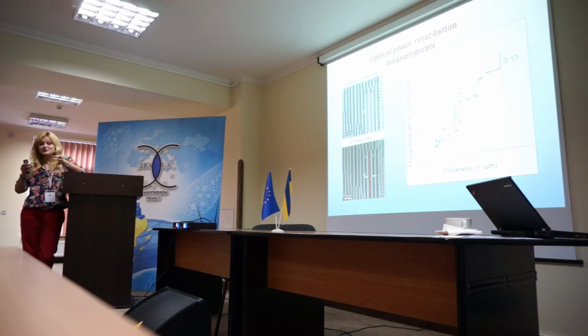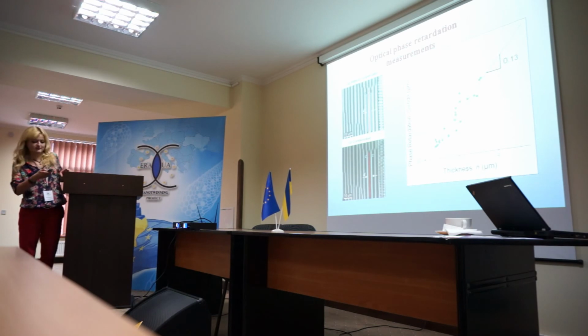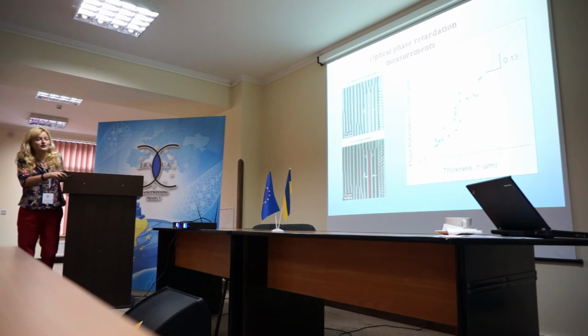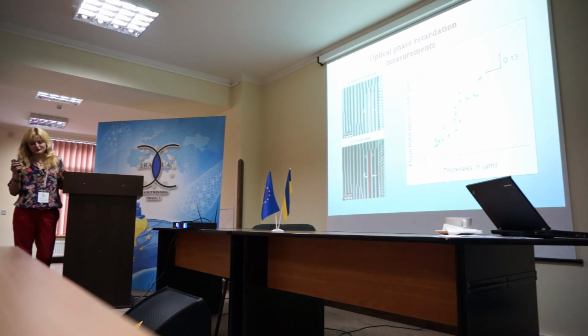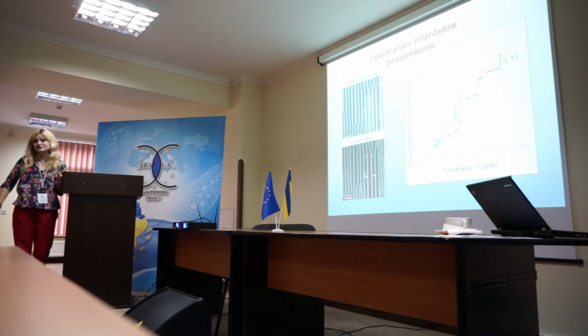We have an optical microscope, we insert a compensator, and when you're looking at the brightest region of the defect, you use a tilt compensator to change it from the brightest to the darkest, and it gives you the phase retardation. Knowing the thickness of the sample, we can calculate the local coefficients in this region. It's just a microscopical technique. I understood. Okay, thank you.